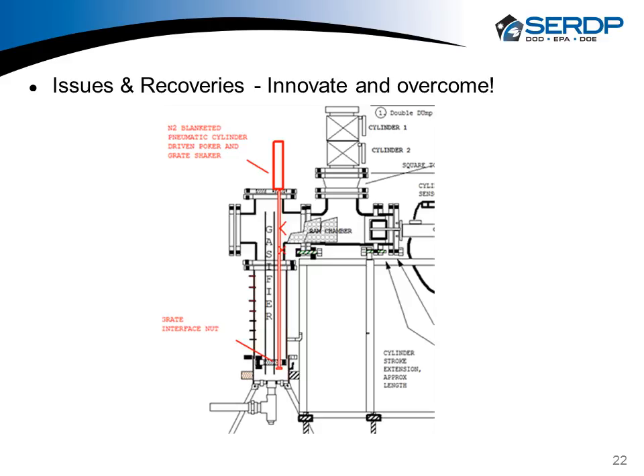The other thing we got out of this is a little benefit. We have a grate interface nut that would give the grate a little kick every time the thing cycled up and down, so that it kept the ash moving through the system. I don't talk about it, but we had a kind of an elaborate ash removal system where we had basically a vacuum source. We could open up these air intake valves and draw the ash out and do a clean out while the thing was operating.